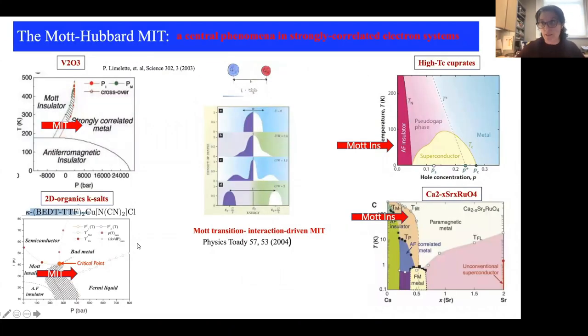So Mott metal insulator transition, or interaction-driven metal insulator transition, is truly a central phenomenon in strongly correlated systems. And here I show the pictures of different families of strongly correlated systems, and you can see each of them is featuring this Mott metal insulator transition. So this includes transition metal oxides, organic salts, high temperature superconductors and strontium ruthenate systems, where Mott metal insulator transition can be either driven by changing pressure or temperature, or you can change the doping of the system, okay?